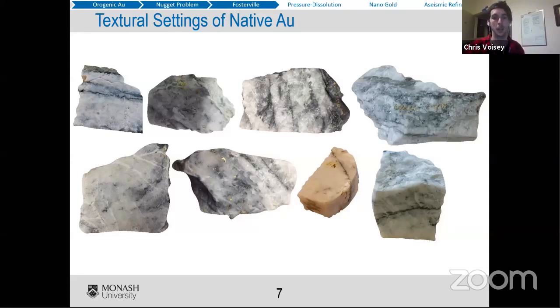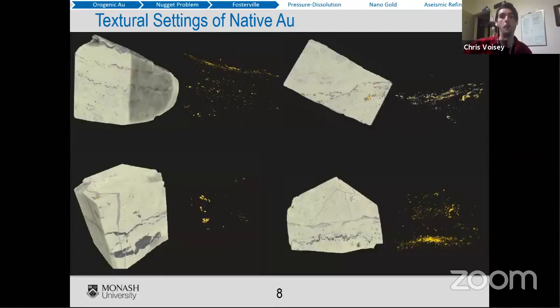We took these samples to a place called ANSTO, which is just outside Sydney, in a place called Lucas Heights, and it's a nuclear science facility. So they have a nuclear reactor that they use a bunch of good techniques with. And what we did with our samples was we did neutron tomography. So you can get a 3D view of what's in your sample. So what I have here is 4 selected samples. These are 3D reconstructions. So the samples are about 4 centimeters cubed.